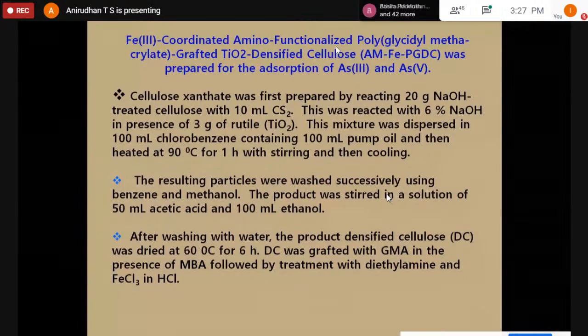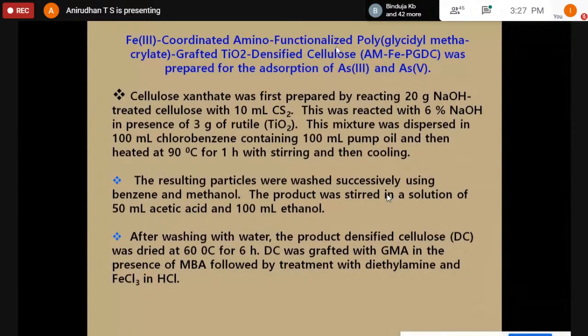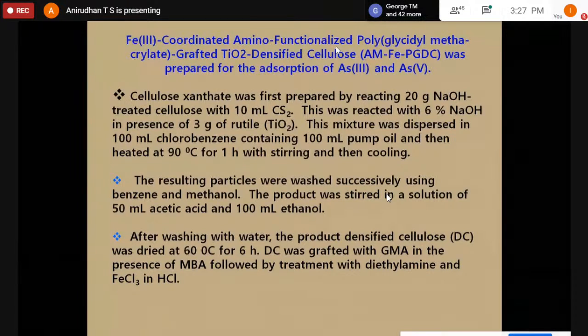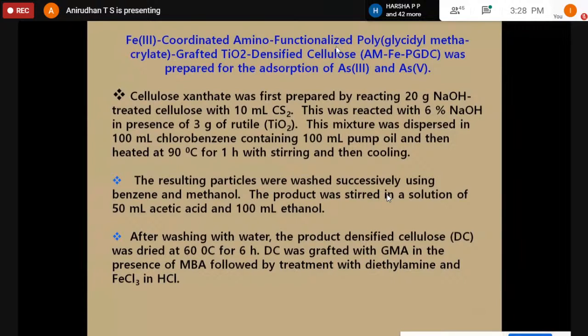You may utilize even anatase or brookite, but we have already checked that within these three forms, the rutile allotrope is a very good material, so we utilize rutile to introduce titanium inside this material. This mixture is further dispersed in chlorobenzene and pump oil so that we have a paste material, which is washed with benzene and methanol, and the product is again washed with acetic acid and ethanol. Then finally it is heated at 60 degrees for 6 hours, and your product is known as densified cellulose.